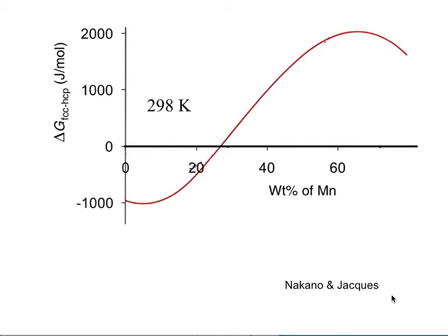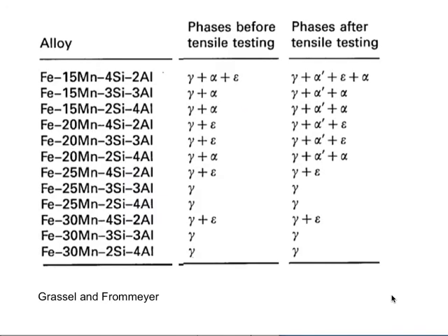Is martensitic transformation desirable in this case? So the level of elongation that we get when it's fully austenitic, because of the twinning subdividing, is much greater than with the martensitic transformation. We were talking about 25% roughly in TRIP steels. But this is ridiculous amounts of elongation. 100% is possible. Okay.